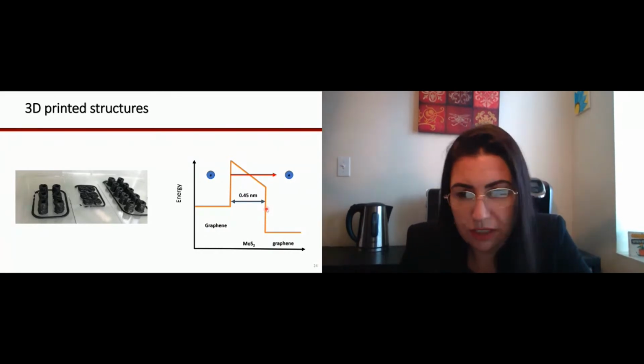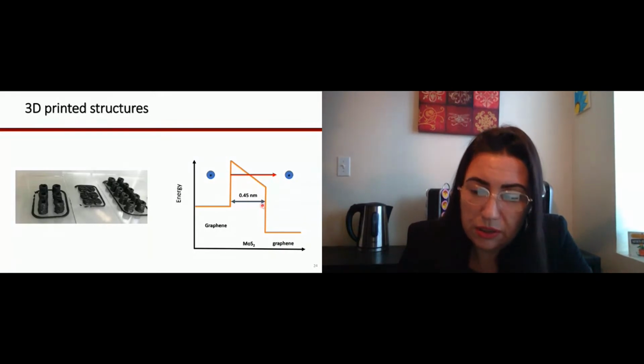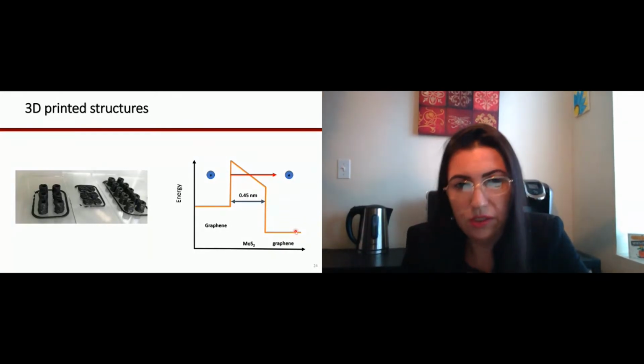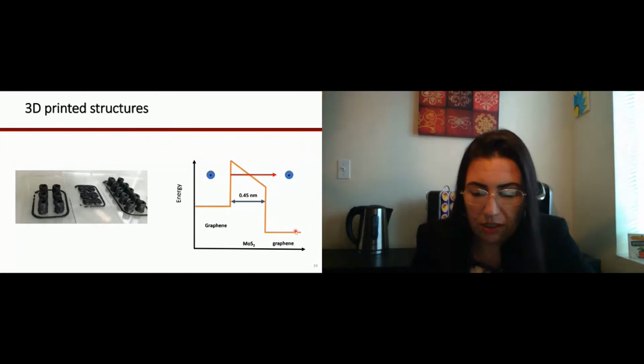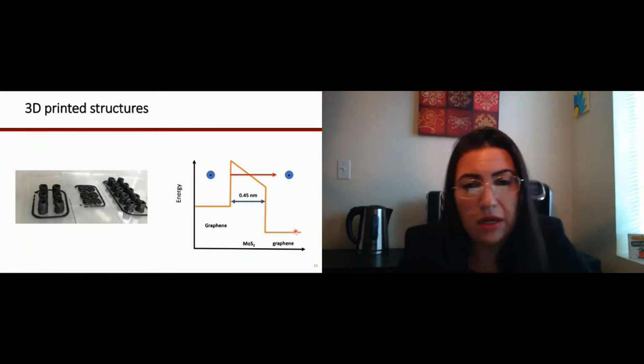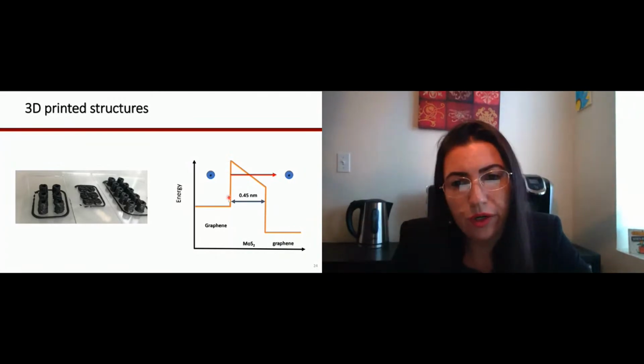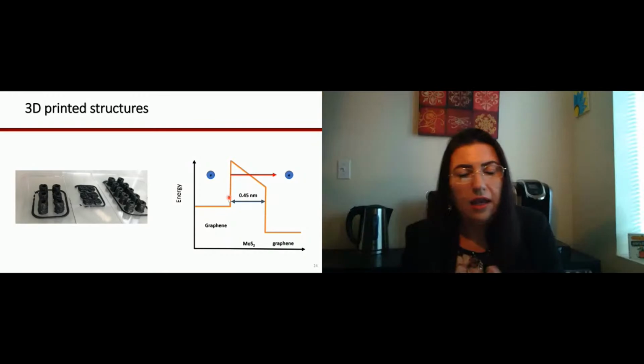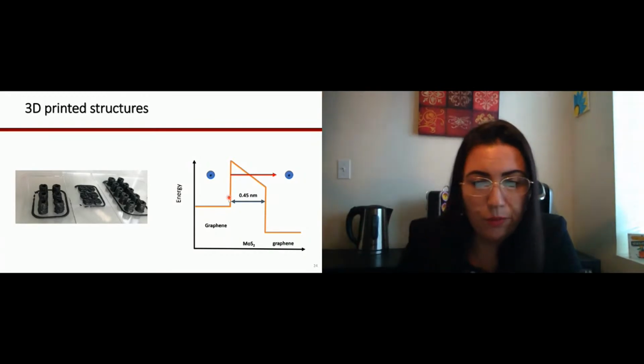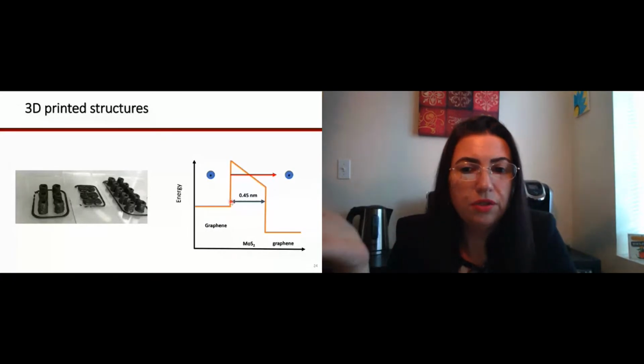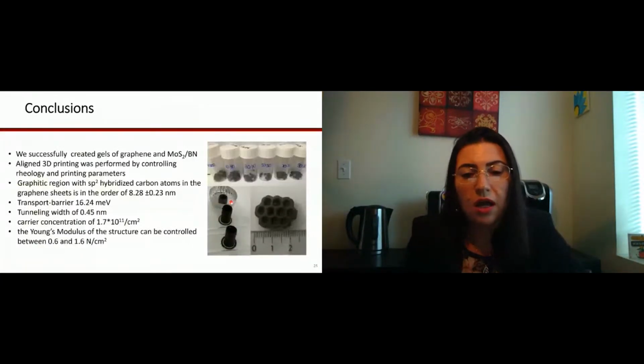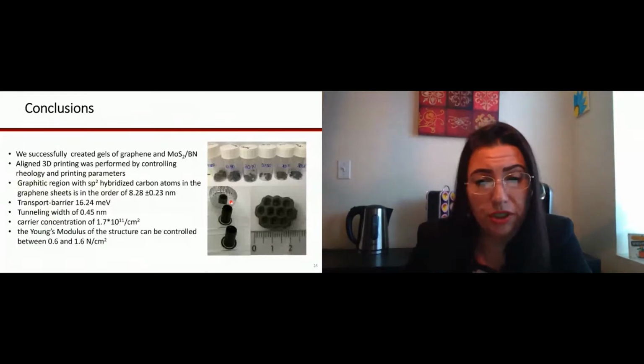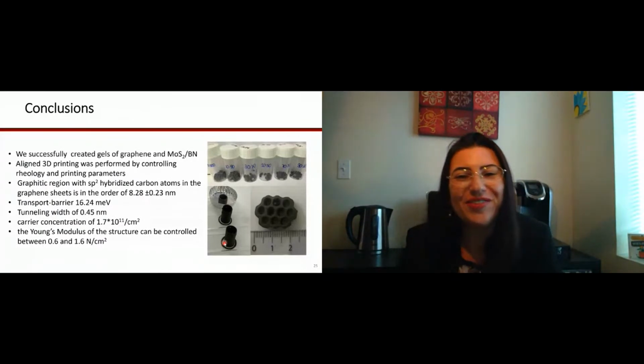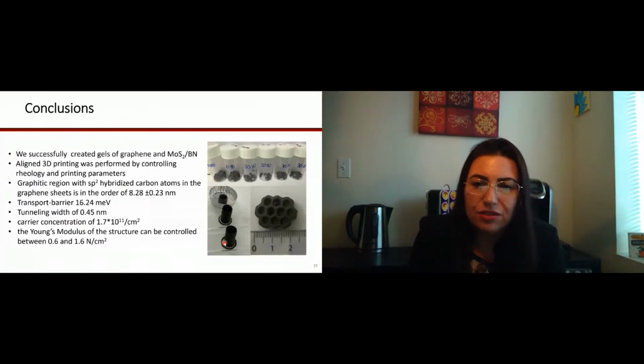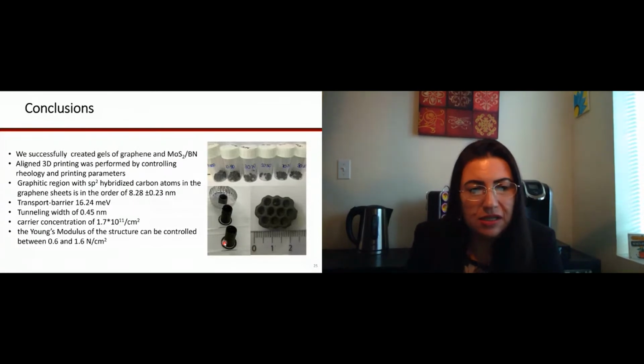In our case, the electron tunnels through the MoS2 and goes to the other graphene. So this is really trying to understand the electronic characterization. And the other thing that we had in the study was the 16.24, which is how much energy is needed for the electron to start flowing and tunnel through the material. So as a conclusion, as you can see here in the picture, there were larger devices printed, with a graphene structure, and there were smaller devices too, as the electrodes and the hollow cylinders.